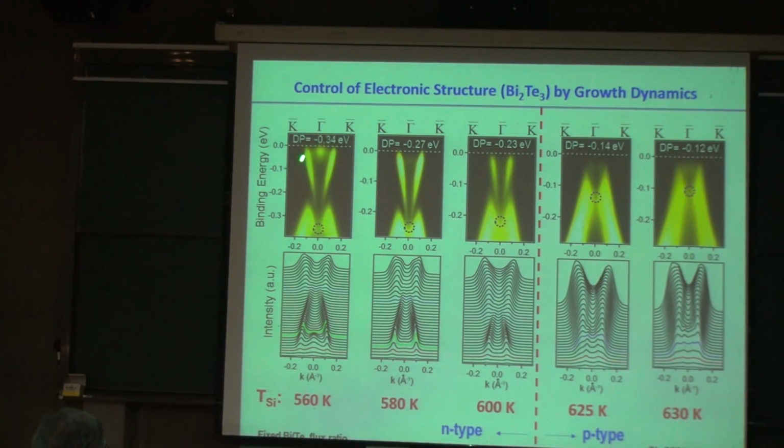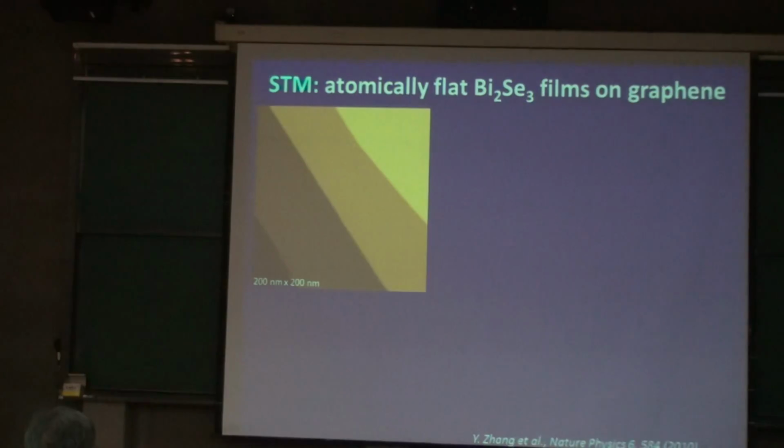So this is an N-type conductor. Now it becomes intrinsic, and now it even becomes P-type. So it is very easy to manipulate the electronic structure by this MBE. For one cycle of the sample growth, we only need 1 or 1.5 days if the experiment goes well. So this can save time compared to the cell flux ratio method. You need several days for one cycle of experiment.